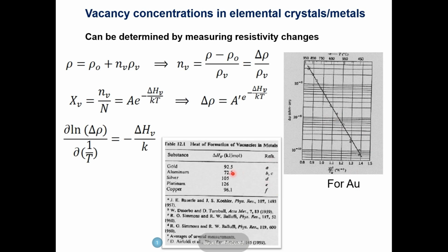Here are the numbers, in kilojoules per mole. Does anyone know the conversion between kilojoule per mole and electron volt? It should come out to be very close to 1 electron volt—I think the conversion factor is 93 or something, I may be wrong but we can look it up. My assumption is for most metals, it's about 1 electron volt. For many of these metals, they've figured out delta H simply by doing this electrical conductivity measurement.